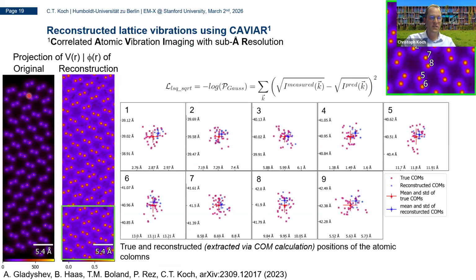Because we have a simulated structure, we can actually know how the atoms have moved. And this would be the displacement of the red dots here. So taking a few of these atoms, given the numbers, and then seeing how they move and plotting their displacements relative to the mean position, this would be the red dots in the original MD simulation. But then the ptychographic reconstruction from these simulated diffraction patterns gives us also displaced atoms. You can see here that they're moving slightly, and these displacements are these blue positions, which don't have quite the amplitude, and they also are different positions, and that makes sense because we don't expect to recover exactly the same displacements.